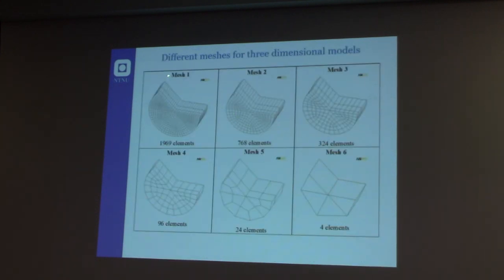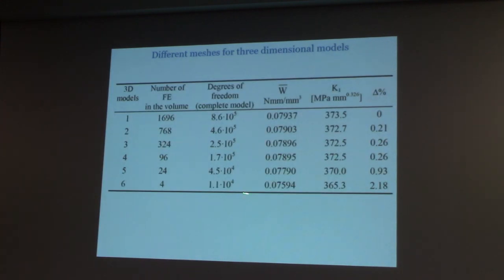So we compared, for example, mesh 1, mesh 2, mesh 3, mesh 4, mesh 5 with different increases of the size of the volume of the elements. We reached the extreme case of 4 elements in the critical radius R0. And if you compare the results with more than 1,000 elements inside the volume and 4 elements, you have a difference of 2%. So it's a very efficient method.